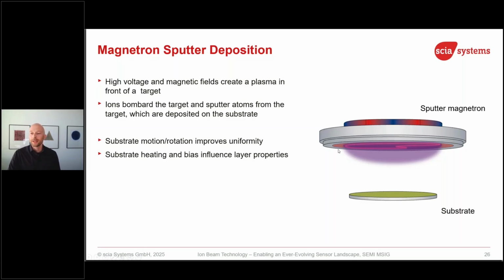So we have a metal target, mostly applying a voltage. Then there are some magnets behind. So we are able, with the magnetic field, to confine electrons, which leads to a higher plasma density. And this high plasma density together with the voltage, we can sputter. So it's the same sputter effect I just explained. So argon ions are hitting this target, and then material is sputtered off and finally deposited on a substrate. And the substrate itself could also rotate. There could be some translation movement. We could apply heating or also bias voltages to that one.